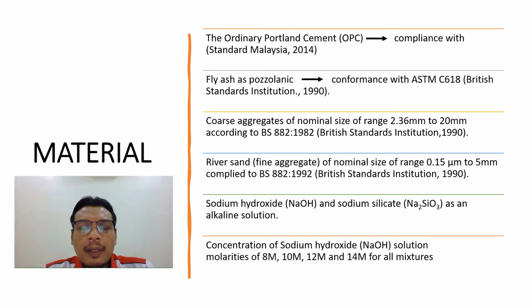Now I'm going to explain the method and material of this research. The materials used in this research are: the ordinary Portland cement, used in compliance with Malaysian Standard 2014, while fly ash as pozzolanic material was used in conformance with ASTM C618. Coarse aggregate of nominal size in the range 2.36 mm to 20 mm was used in producing concrete according to BS 882-1982. River sand as fine aggregate of nominal size in the range 0.15 micrometer to 5 mm was used in this study and complies with BS 882-1992.